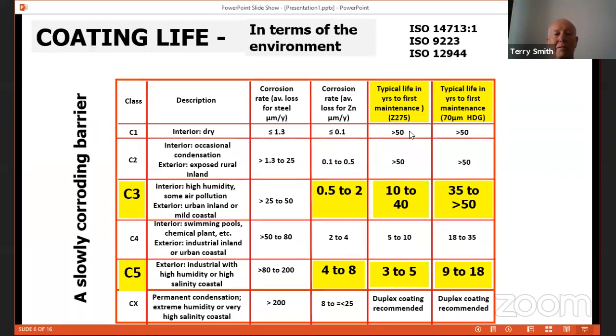This is the typical table that's given out in these three standards. You're looking at C1 to C5 or CX environments. The more aggressive is obviously C5. If you look at C3, for instance, the corrosion rate of zinc is about 0.5 to about 2 microns a year. And you go down to C5, you're looking at 4 to 8 microns a year. A Z275 would last between 3 to 5 years, and hot-dip galvanizing at 70 microns would last between 9 and 18 years.